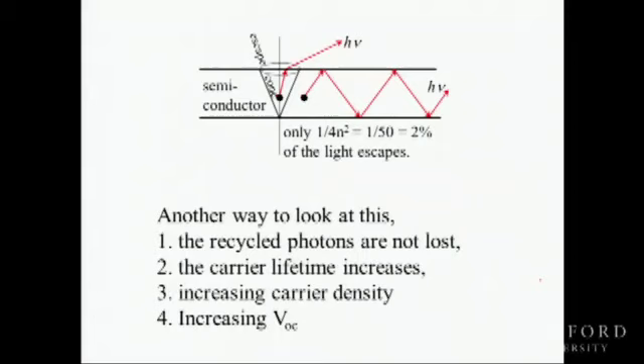Now, here's a way to look at this. You get reabsorbed. The recycled photons are not lost. They are reabsorbed. Effectively, you recreate the electron hole pair. Therefore, the carrier lifetime, you haven't really lost the electron hole pair. The effective lifetime increases. That increases the carrier density, and that increases the open circuit voltage. It's one way to look at it.